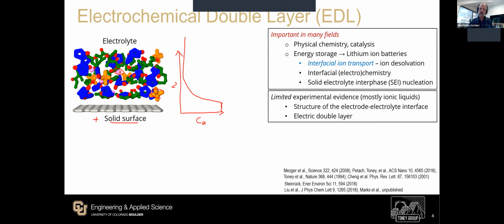we're going to move an ion here that's happily solvated across the interface, and it's going to intercalate into the solid surface. So exactly what happens at that interface is crucially important. How these solvent molecules, how the cations and anions are arranged can have a big impact on that. And perhaps the strongest manifestation is that if you have preferential adsorption of one of the species, they can block some other reactive species from ever getting to the surface. And then you can create effectively kinetically stabilized windows that, for example, can expand the stability window for water.